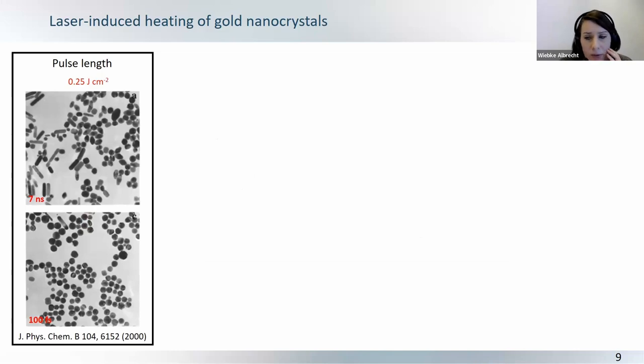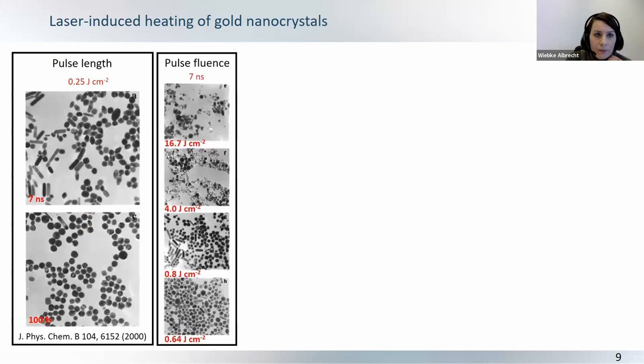But, of course, also to keep in mind that you heat for a longer time, and this will become critical later on as well, the time you give the nanoparticle for heating. Then, of course, the pulse fluence has been seen to be very important, because it's, as you know, directly related to the temperature you can achieve.